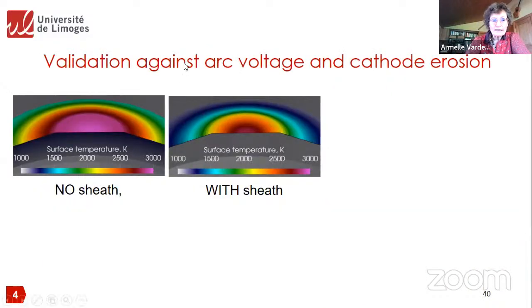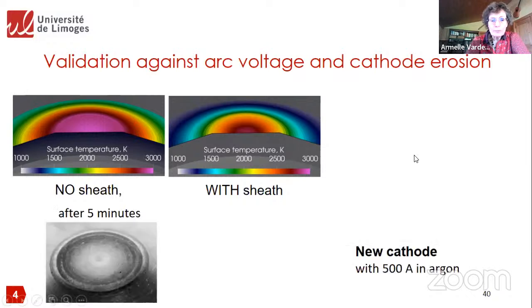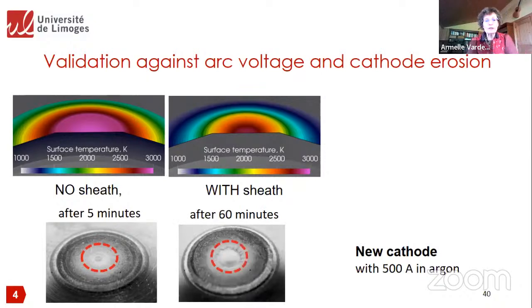Yes, as you will see here, you can see the distribution of temperature of the cathode tip without the sheath model and with the sheath model. And if we compare it with a new cathode that has been operated for 5 minutes or for 60 minutes, you can also see some melting of the tip of the cathode, and the higher temperature is well predicted by the sheath model. It's assumed that this melting is produced by the evaporation of the dopant, but we have not taken into consideration the diffusion of the dopant in the cathode and its evaporation. This is for the future.